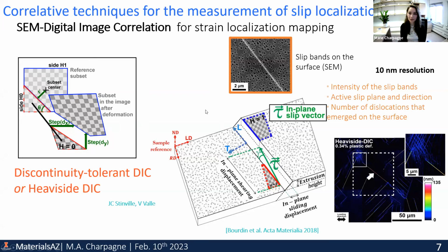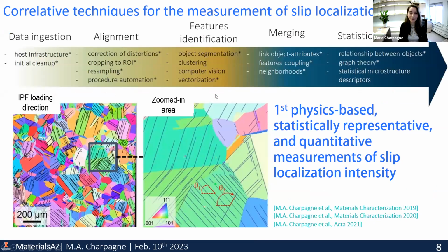So now that we can map what we're interested in, meaning this discontinuous strain field and those slip bands, the question we naturally ask is, what's the linkage with the material microstructure? As you can see here, these planes are related to the orientation of the crystals, and so it's not random; we actually try to understand now how this field of slip bands is connected to the microstructure. So to do this, we need to, of course, map the microstructure, and there are commercially available techniques for this. The most powerful one is electron backscatter diffraction, EBSD. So this is an example of what maps we can acquire with this. Here, each crystal within our region of interest is colored according to what crystal direction is along our loading direction, which is horizontal in this example.